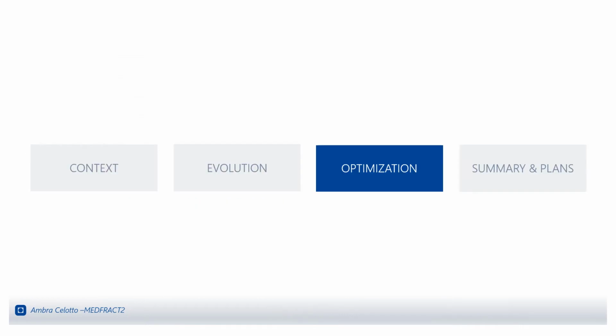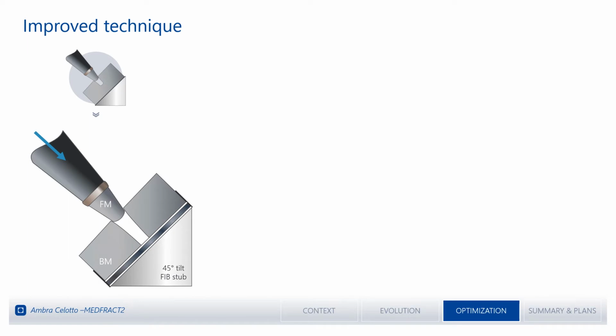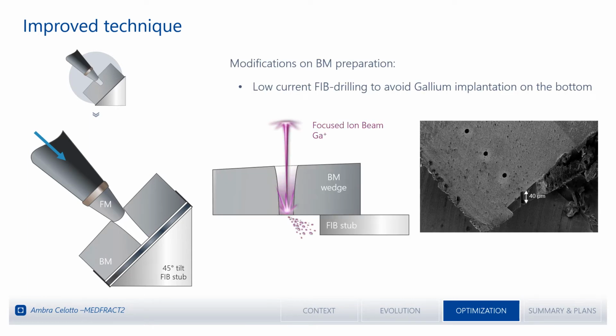So let's see now the optimized version. The main difference with the previous setup now is that instead of making a blinded hole, we'll drill a through hole. And this is made by having an empty space under the base metal wedge while we are drilling the hole with the FIB. This will make the gallium free to evacuate from the bottom. And by also using a lower current for doing this, the general amount of gallium on the bottom of the joint and on the walls of the holes is expected to be reduced.